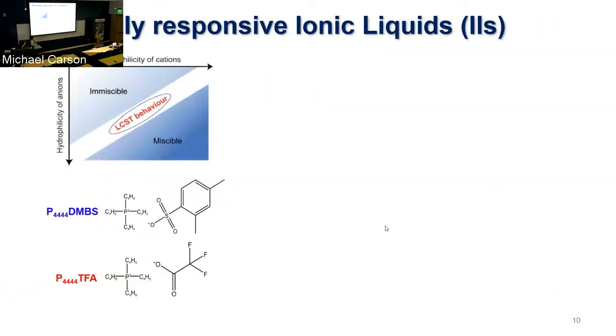So these are some of the different ionic liquids. These are being synthesized by Professor John Reynolds' lab here in chemistry. And the most interesting part is that this phase behavior requires a very, very subtle balance of hydrophobic and hydrophilic functional groups in your ionic liquid. So for example, with this structure, one of these methyl groups, the ionic liquid no longer exhibits that phase behavior. So it's a very, very small balance of hydrophobic and hydrophilic that gives us that critical temperature.